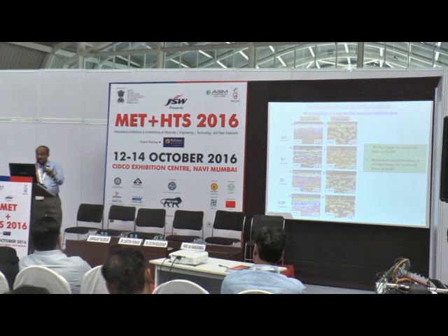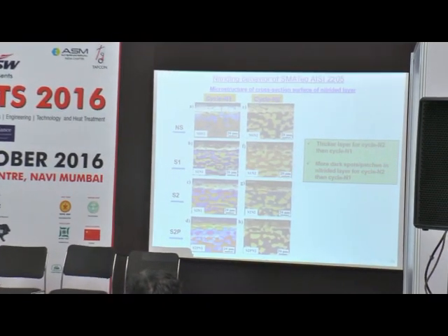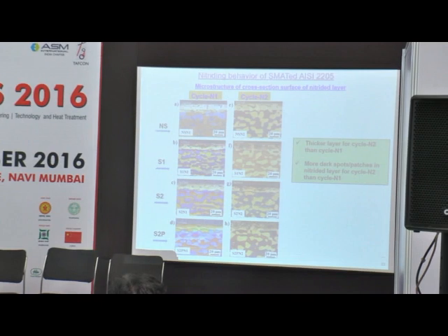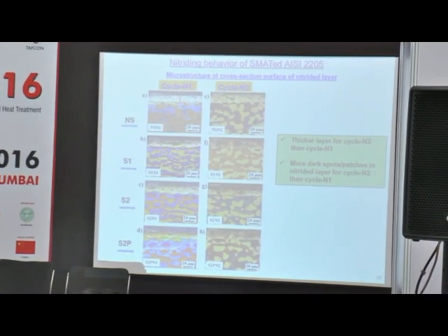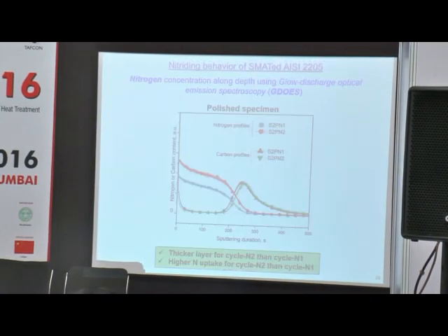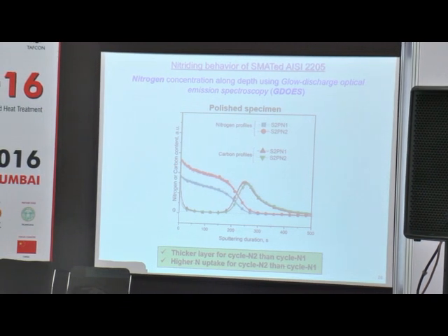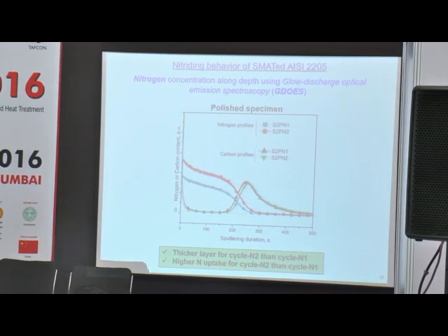In all cases, you got the higher case depth compared to the lower sputter time. Even though my plasma nitriding duration was the same, everything was the same, only the sputter cleaning duration was different. And that drastically affected my nitrided layer thickness. There is another proof for that.